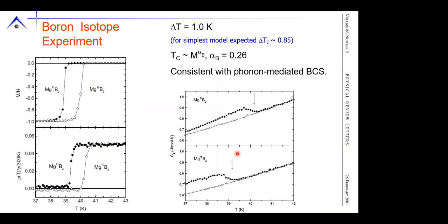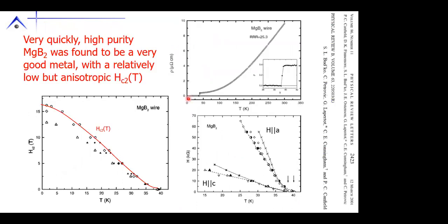and this was fully consistent with phonon-mediated BCS. So the first paper published on MgB2 immediately made it clear that this was an extreme example of phonon-mediated superconductivity. Now, with samples like this, then we can measure out Hc2. We can see it's a very good metal. We can see Hc2 is relatively modest for the pure material, and has a moderate anisotropy because we developed a technique for inferring anisotropic Hc2 from polycrystalline samples.